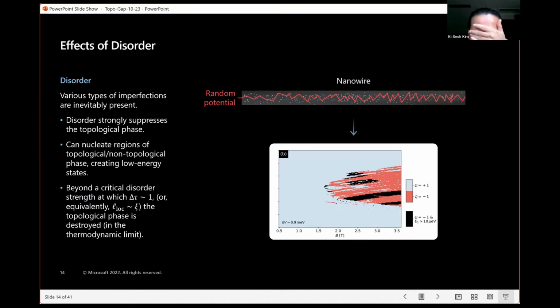So in this case, if I recall the topological insulator with disorder, in some parameter range we can observe the so-called topological Anderson insulating phase. So in this case, what happens? Is there an analogous phase? Yeah. So okay, this is a one-dimensional system, not a two-dimensional system. Because this is a 1D system, actually all states are ultimately localized. Okay, so other than potentially the phase transition zero energy states, all states are localized. So in that sense, it does have that property of an Anderson insulator. However, even though all states are localized, the system may be topological or non-topological.